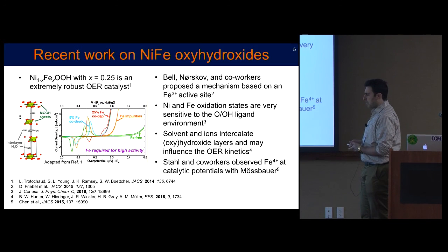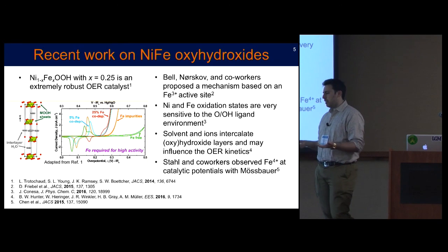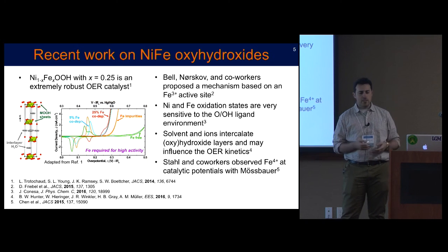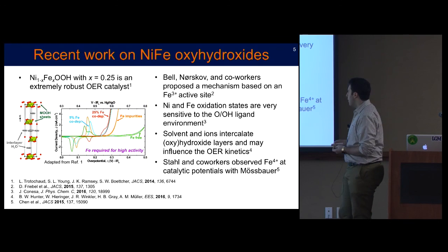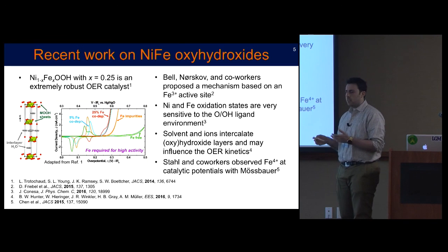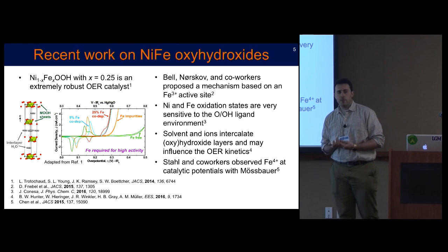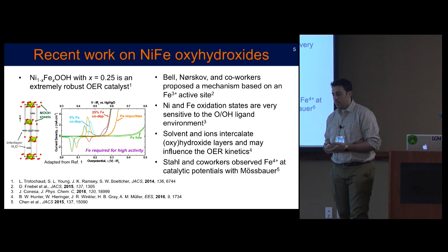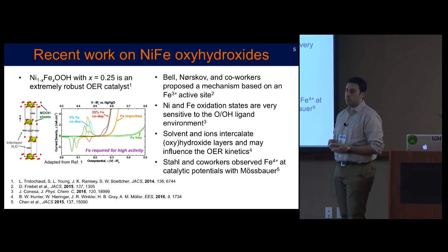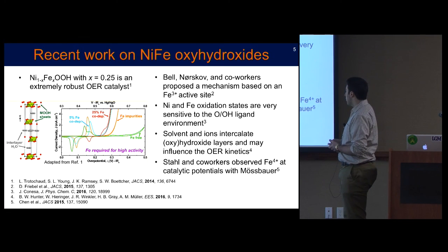There was a joint experimental computational paper shortly after these experiments were published that claimed that under working conditions, the oxygen evolution active site for this material was an iron 3 site. However, shortly thereafter, the group of Shannon Stahl at Wisconsin-Madison, who we ended up collaborating with, did an operando Mossbauer spectroscopy experiment under the working electrocatalytic conditions, and they saw a steady state and significant population of iron 4 under those working conditions, which of course directly contradicted the previous study predicting iron 3 as the active site.